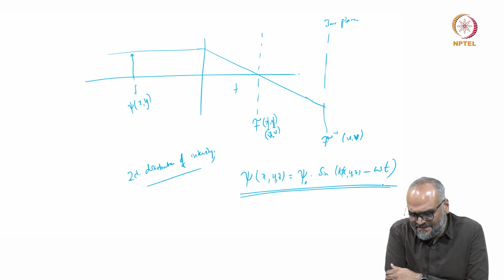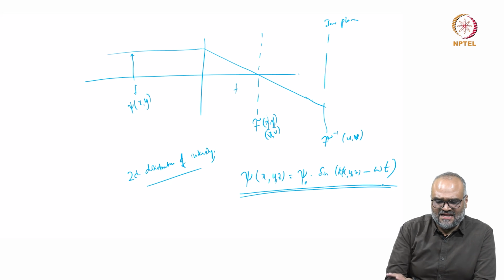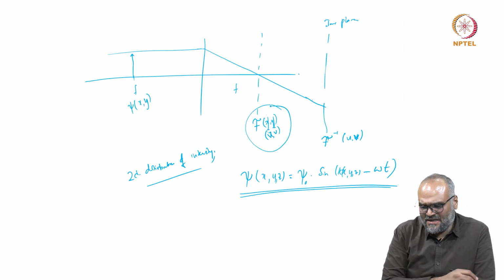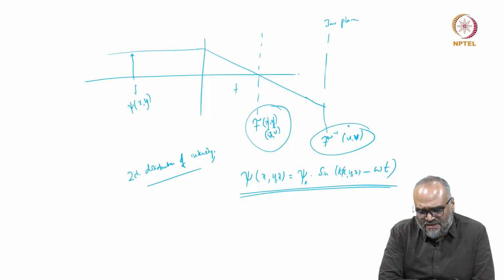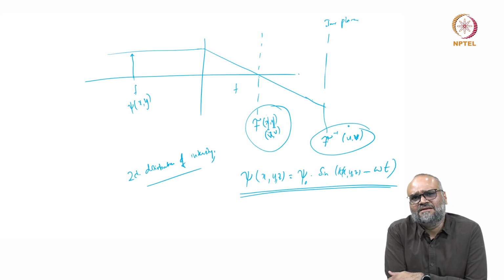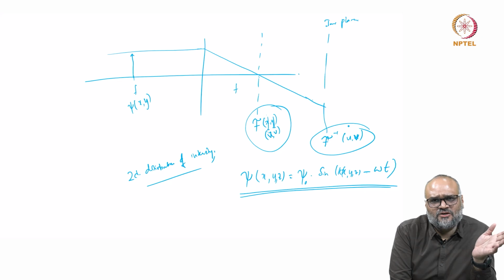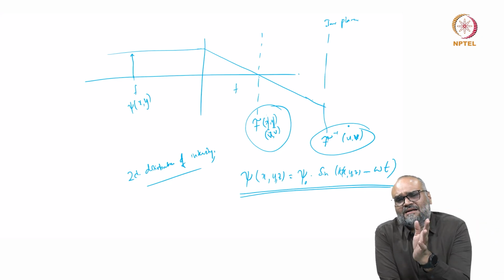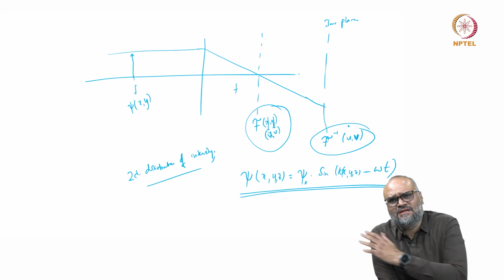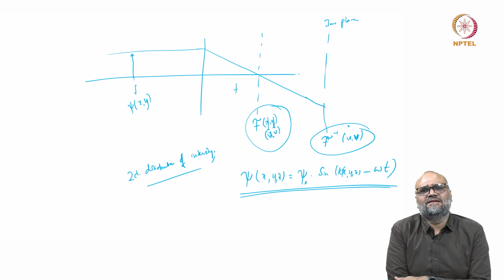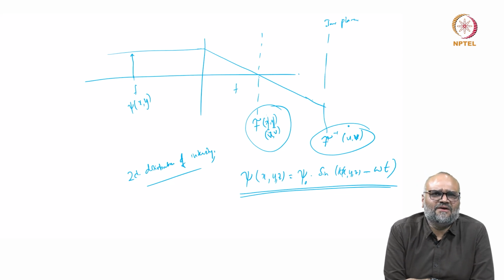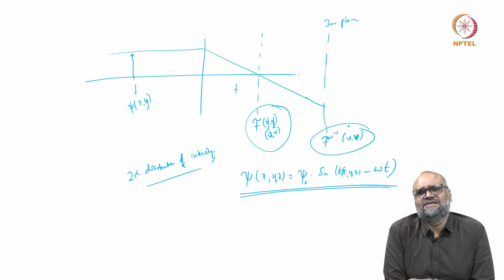So when I form an image, I am essentially transposing it to the Fourier transform at the back focal plane, and these again form an inverse Fourier transform at the image plane. So you can look at a lens as a mathematical operator which switches from the spatial domain to the frequency domain, and an inverse Fourier transform from the frequency domain again to the image plane. So with this background, if I now start looking at how a periodic sinusoidal waveform looks like, let us try to see how an image is formed and how do you interpret these images.